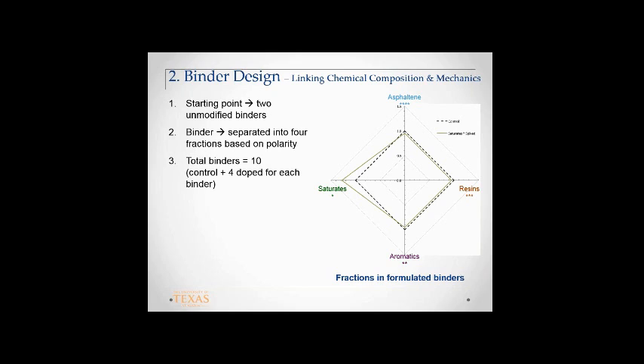Next step, we dope the original asphalt with one fraction at a time. If you look at these four fractions, saturates, aromatics, resins, asphaltenes, they are present in a certain proportion. These proportions are different for each unique binder. What I do is take the saturates that I got and put them back in the binder. I spike it with saturates, so I shift the balance. You see this dotted line? This is the original asphalt binder, a nice balance between all four components. I spike it with saturates, so I have more saturates in this one.